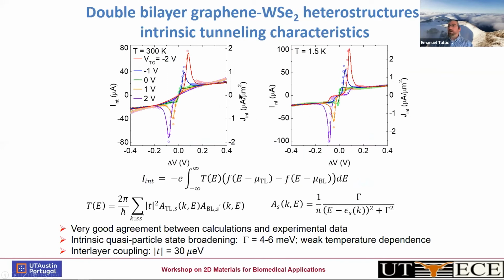These types of tunneling characteristics tend to be very robust with temperature. So I'm showing here data from 1.5 Kelvin to 300 Kelvin. And this is something very distinct, for instance, from electrons in III-V compounds or silicon-germanium heterostructures, where the tunneling characteristics seem to be very sensitive to temperature. And that has to do basically with the 2D confinement of electrons in graphene. And we can model this quantitatively, and there's good agreement between the experimental data and simulation.